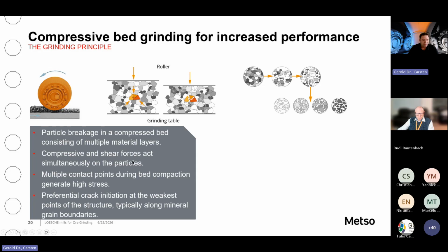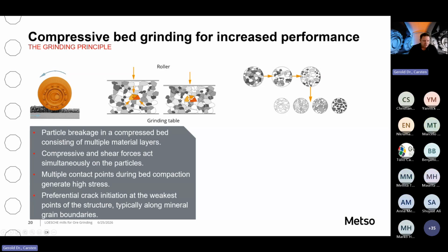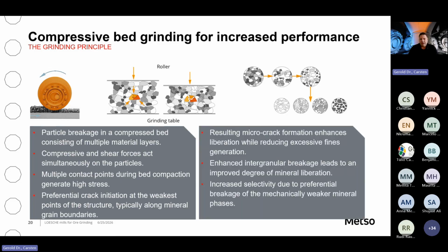It's a combination of compressive and shear forces, which act simultaneously on the particles. We have this fluid-like stressing from all sides on the agglomerates, and therefore we see preferential crack initiation at the weakest point of the structure, which is typically along the mineral grain boundaries. Resulting microcrack formation enhances liberation while reducing excessive fines generation. It's an enhanced intergranular breakage that leads to an improved degree of mineral liberation, and we see increased selectivity due to the preferential breakage of the mechanically weaker mineral.